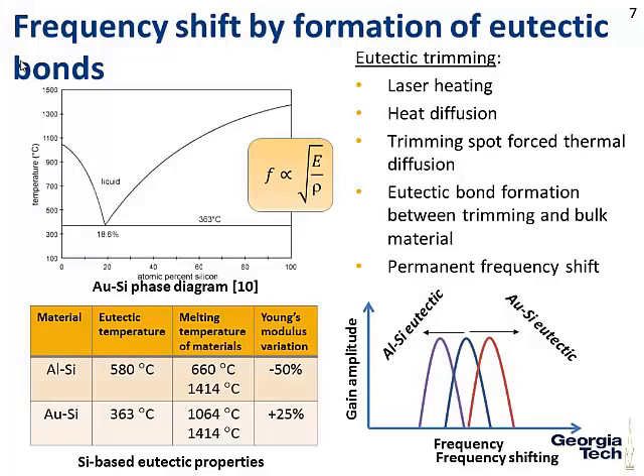Again, as I said, if you look at this graph here, you're going to see that for aluminum silicon, the Young's modulus is actually smaller than the Young's modulus of the silicon that was there before. So if you form an aluminum silicon eutectic, the frequency is actually going to be lower than what it was before. And if you have, for example, gold silicon, the Young's modulus is actually larger than the Young's modulus of silicon. So in that case, your frequency is going to increase, going from here to here.